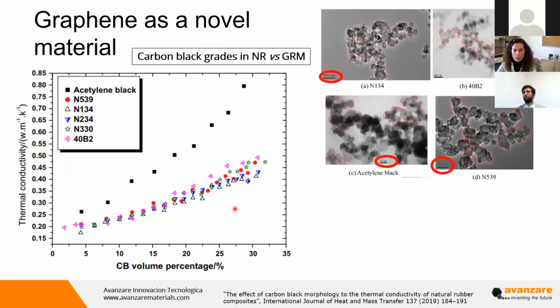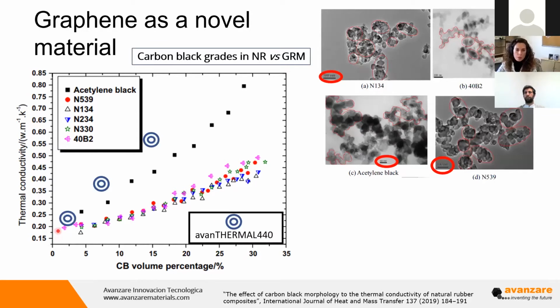So to see another example to analyze this, there is a recent paper of natural rubber working with different carbon blacks. We can observe the morphology of the aggregates of these carbon blacks and the thermal conductivity of these samples according to the volume percentage of the load. If we compare these results with some obtained in natural rubber with materials from Avanzare, we can observe that there is a significant increase with a lower quantity of this material. Why can we explain this?